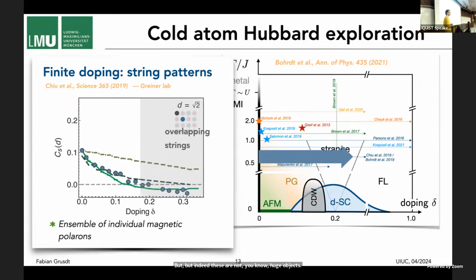All right. So we also looked at other quantities like the spin correlations, going back to this idea from before that around the dopants they saw these diagonal correlations that change sign. And indeed, this is now just looking at this diagonal correlator, but not post-selected to where the holes are. If you just average over everything, and don't ignore the holes, you can see these diagonal correlations change sign. And again, this is around 20% doping, maybe a little bit before. But this basically shows us that somewhere around here, indeed, these ultracold atom experiments also see a qualitative change of behavior. And in fact, here at low doping, we can again explain the sign change and so on from just adding in these simple strings. And that is without letting the strings interact, which in reality would surely eventually happen.